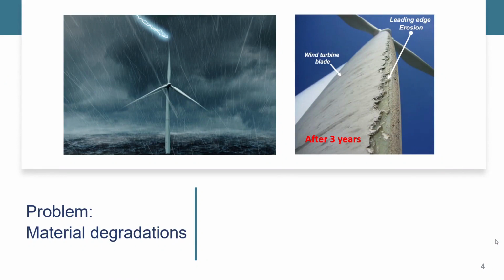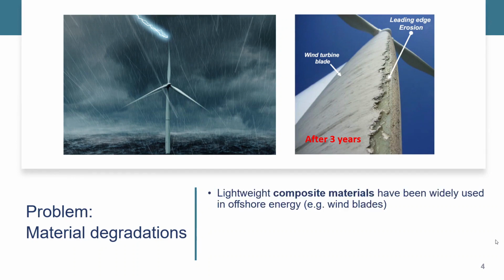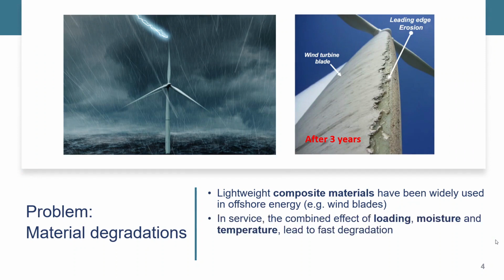One of the main challenges is to develop resilient materials for offshore energy. As you know, lightweight composite materials have been widely used in wind turbine blades. In service, the turbine blade can experience very extreme weather conditions, including the combined moisture and temperature effects. This includes some extreme loading cases, like high velocity impact of liquid, which can cause rapid wear of the wind turbine blades. Typically after 3 years, you need to send people to repair the wind turbine blade.